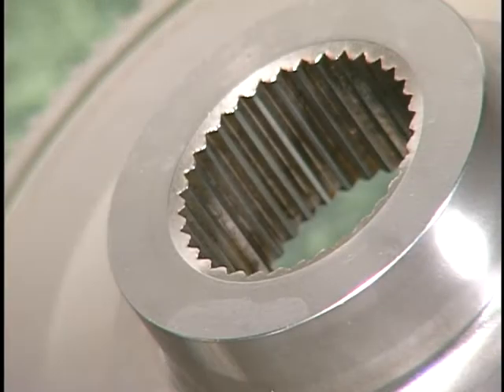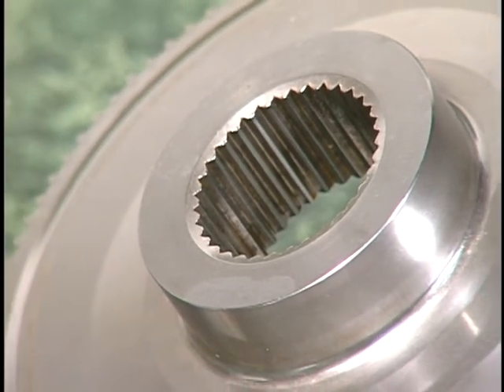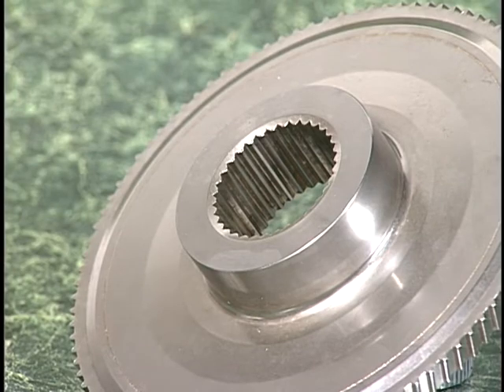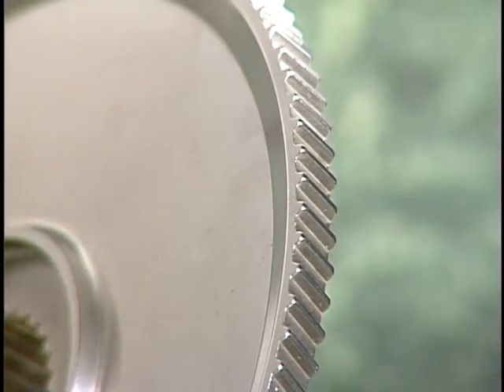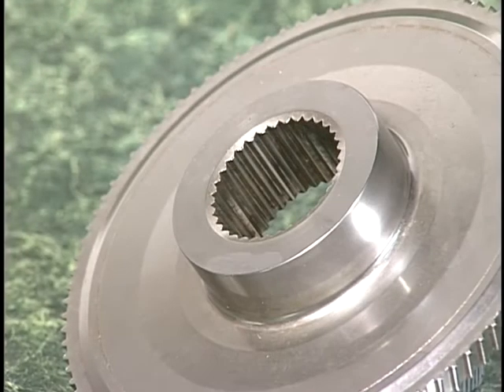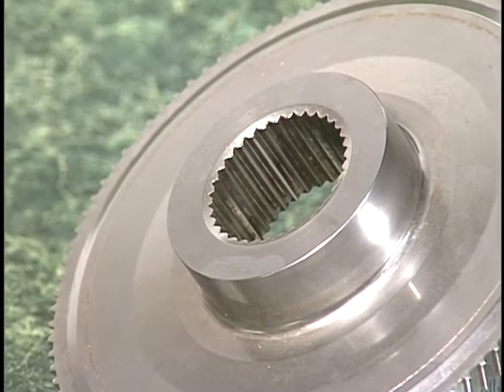The external helical teeth and straight involute splines are molded as a net shape and are particularly difficult to process via warm compaction. Using this process to produce the part, which had originally been designed as a forging, provided a 30% overall cost savings in a net shape part that surpasses the performance of a machined forging. Secondaries are limited to vibration deburring and some machining.